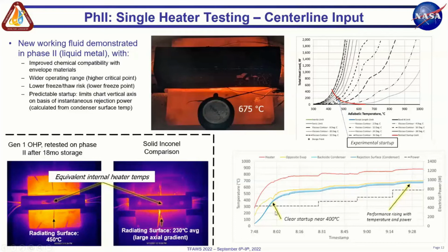There's a time series on the right. Could spend more time than we have talking about this chart, but the gist is we have instrumentation in the heater, and then opposite the heater, we're calling opposite evaporator, and then some of the condenser surfaces. As we rise in the electrical power steps, and as the temperature of the structure comes up, you can see a feature here: as the system's getting hotter, you see a dip in the opposite evap temperature and improvement in the overall structure's uniformity as measured from that evaporator out to these tips of the part, about 3 inches away from the heat input source.